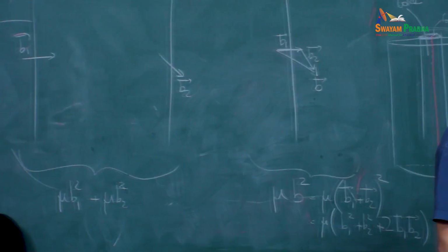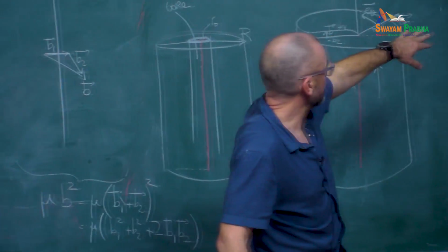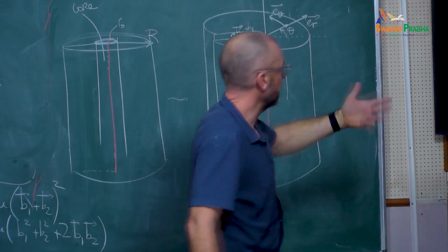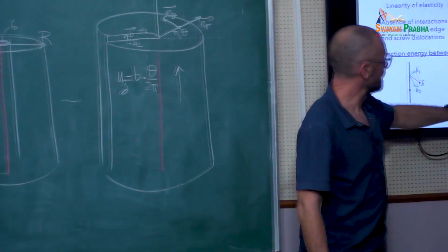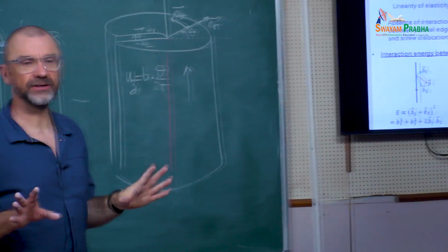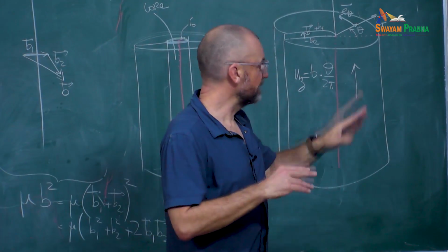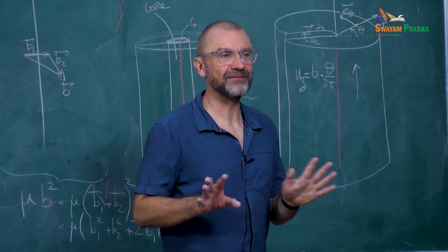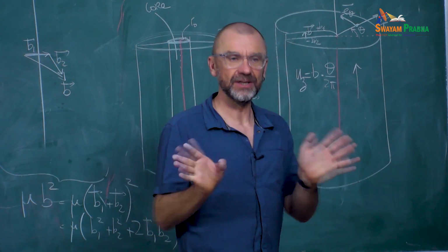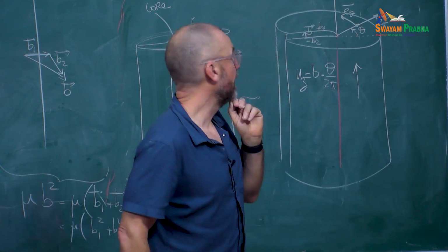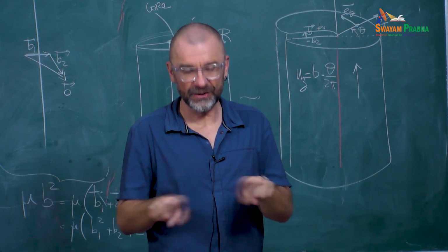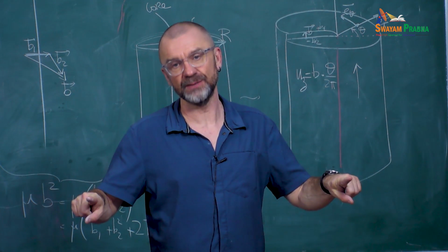So I think it's what I have here. So we said the mix with the linearity, and then that's the Frank rule, and exactly the example that we said. Two dislocations attract each other. So it's a very approximate calculation, right? But in practice, I've never seen a case where it didn't apply, even if we've done the calculation in a very simple setting. Well, if it is equal, then it's the same whether they are on top of one another or if they are separated.